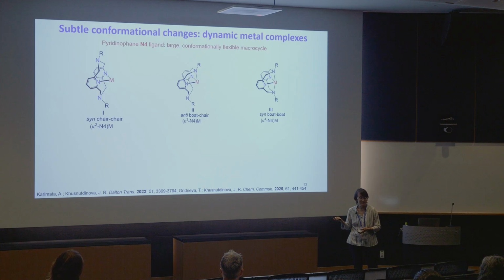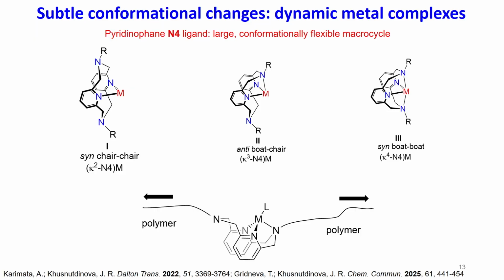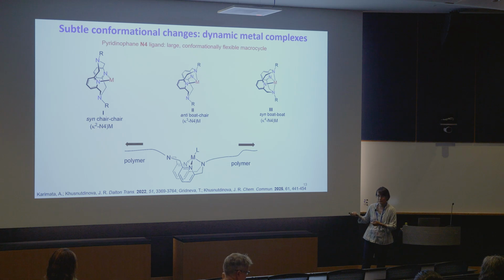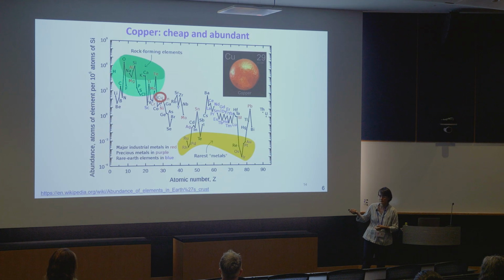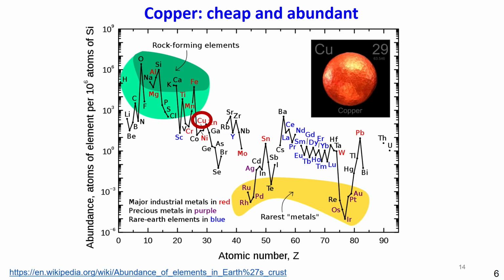So the next idea was very simple, maybe even too simple. Why don't we attach this ligand through these 2 points on the nitrogens to the polymer chain? We introduce the metal and then we stretch it. Would we be able to affect the properties of the polymer sample that contains this metal complex? So we started working with this system. We had to screen a few metals before we found the right one for us, and that was copper. Copper is cheap, it's abundant, it's very easy to work with. And copper complexes had a number of good properties that we were looking after.